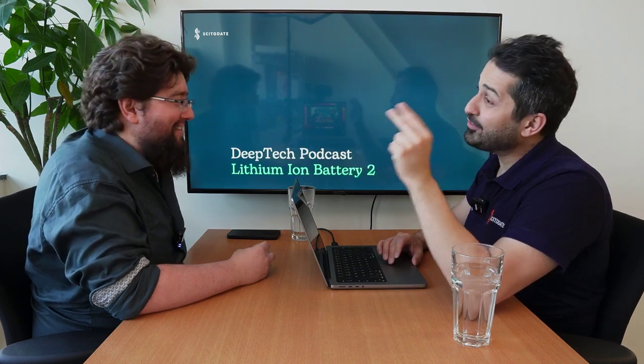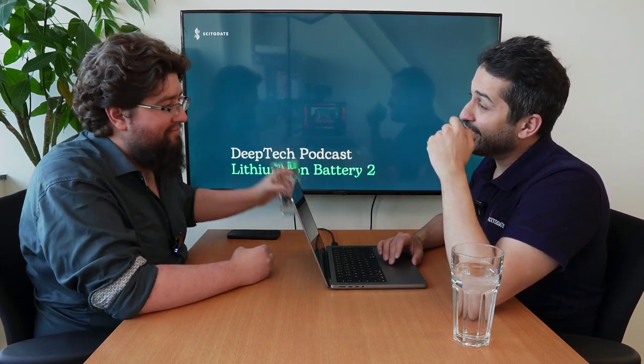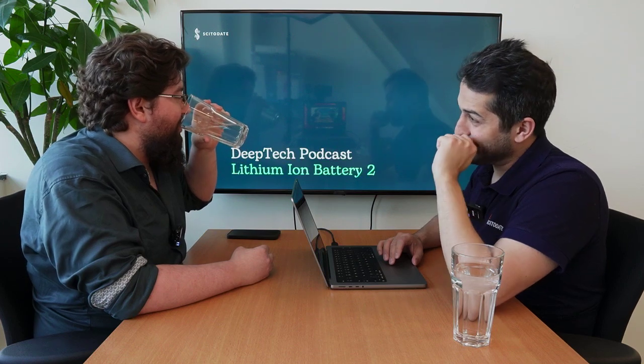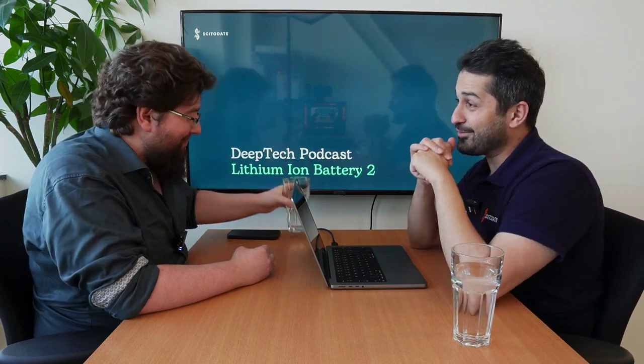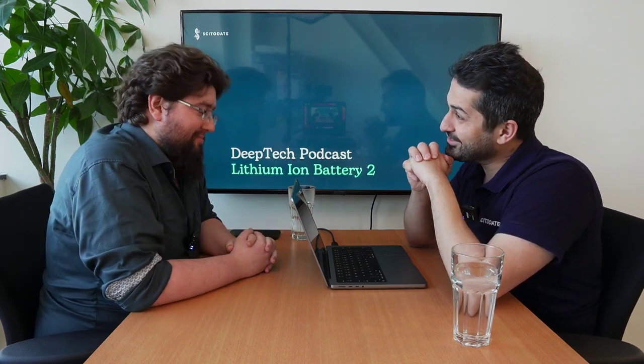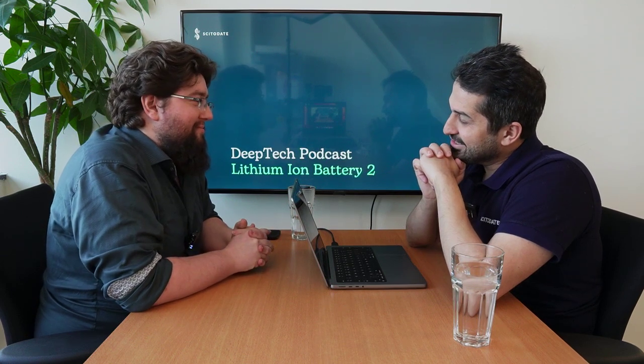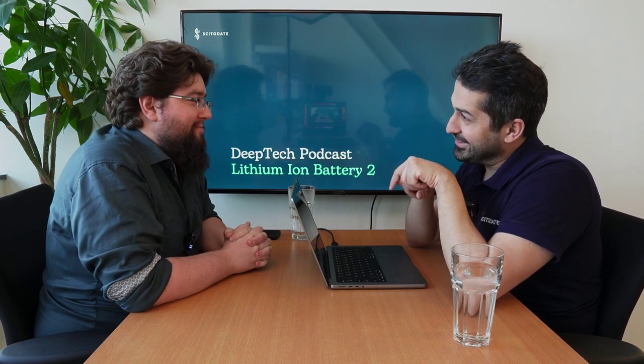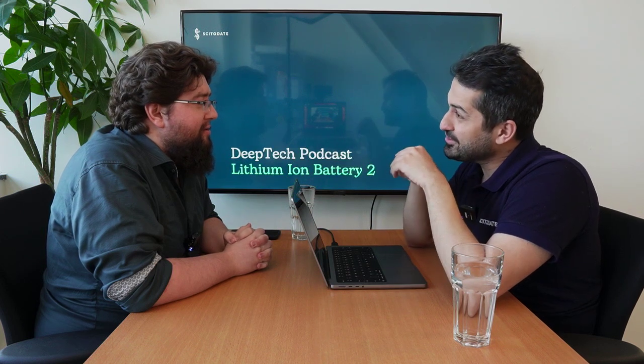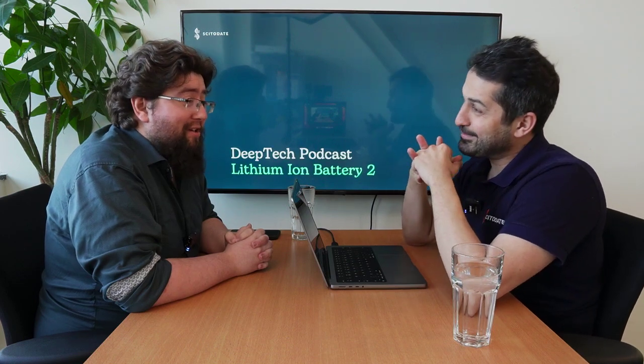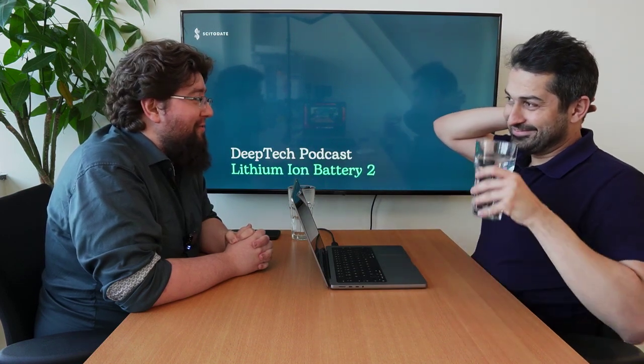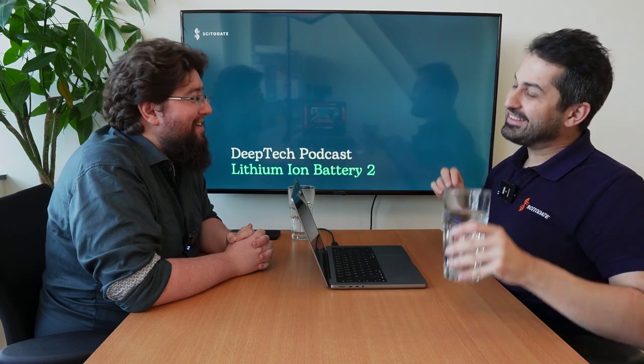Okay. So the second way that this can happen is if you charge it too fast, rapid charging. Now you see all the phones have this 100 watts, and the cars they say 15 minutes from 0 to 80% charge, but it creates plating. How many minutes did you say? 15 minutes, 0 to 80% sometimes. I didn't know that it got that good. That's as fast as a phone now, charging a car. That's amazing. But in 1 year of doing it, you just lose 20% of the capacity, you know what I mean?